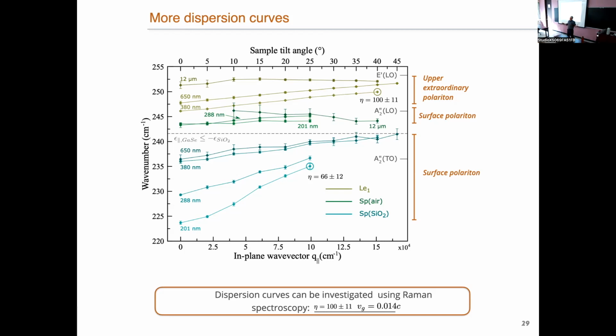So in order to achieve confinement on the phonons, you need to go orders of magnitude lower in thickness. What I just presented was a 650 nanometer thick sample. That's huge. To get confinement on phonons, you need to go to tens of nanometers. I don't know the exact number, but that's much more difficult.